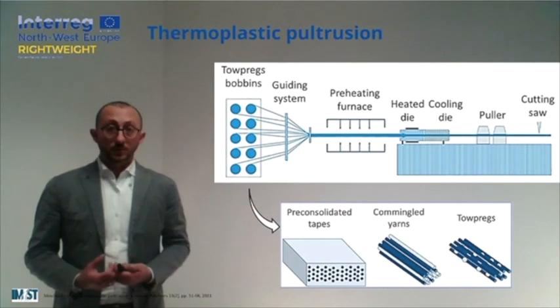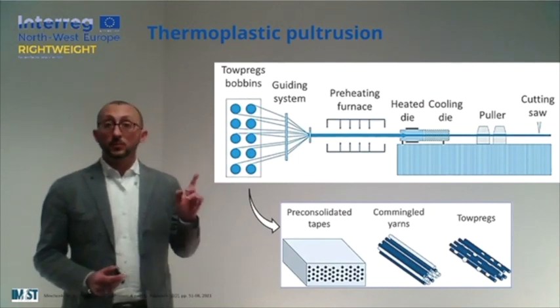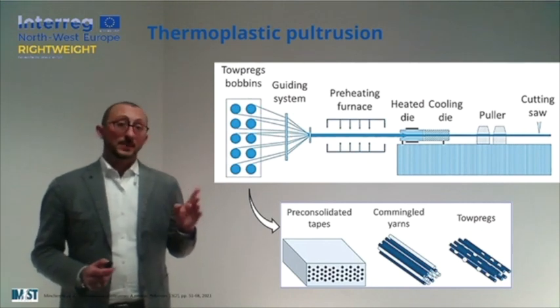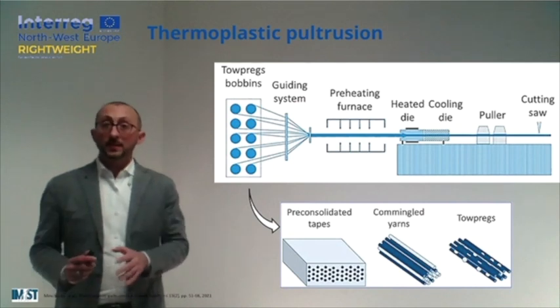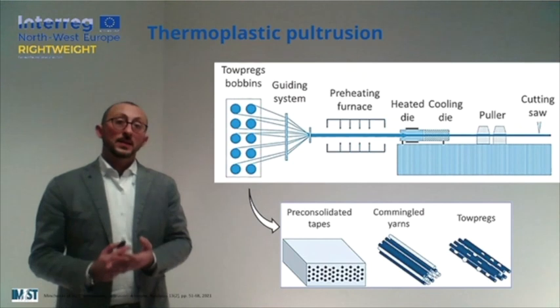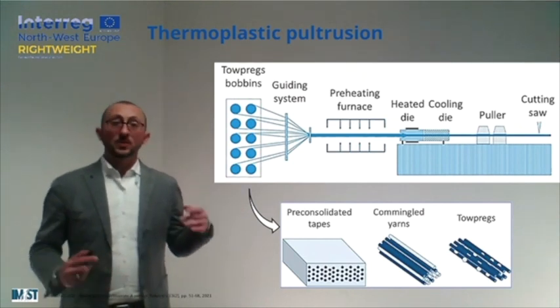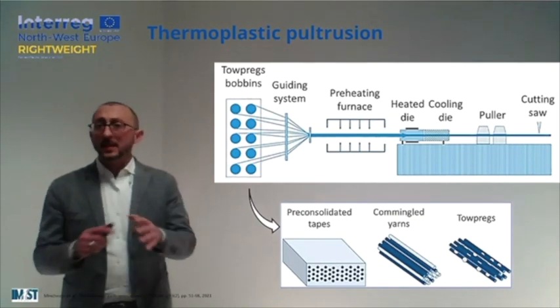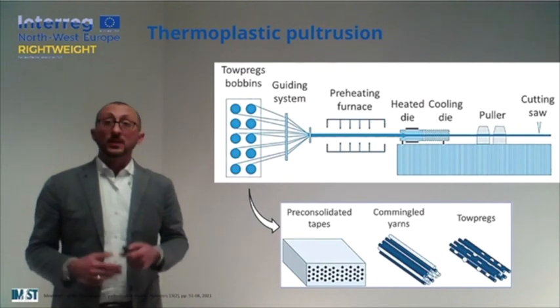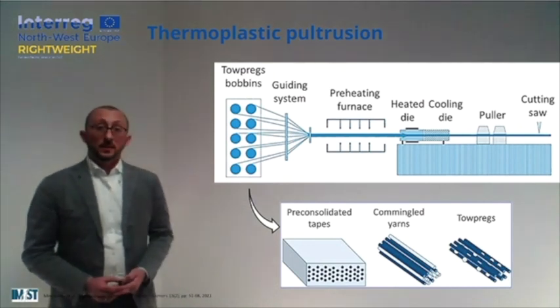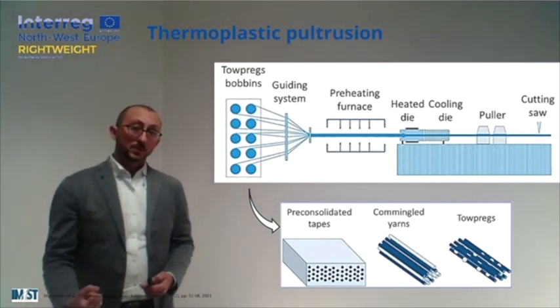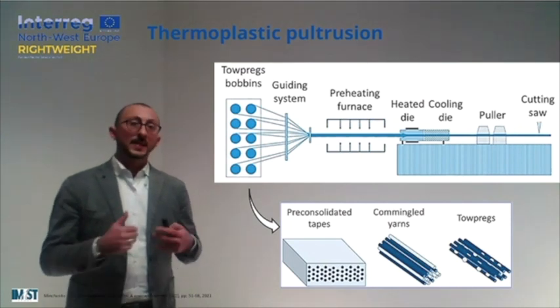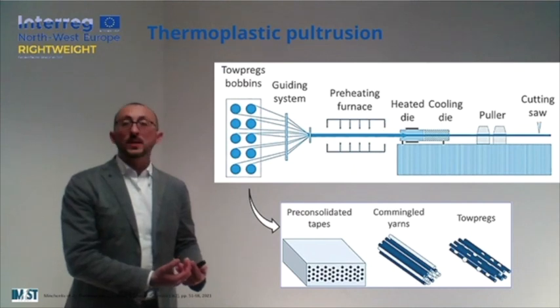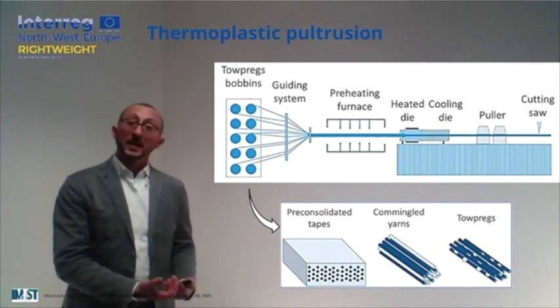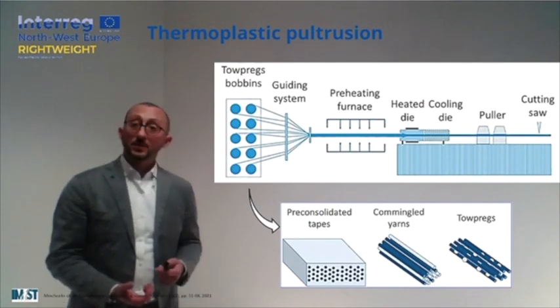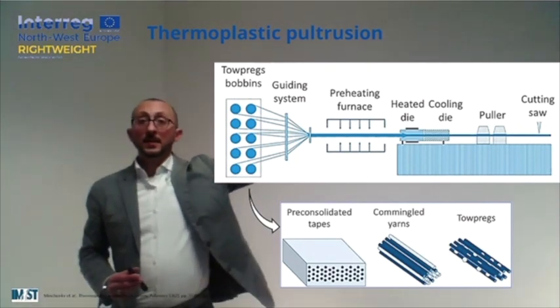So, in the most common approach, the starting point of our pultrusion line is given by the same creel rack, but on that creel rack a combination of matrix and reinforcement is placed in the form of tapes or commingled yarns or towpreg, but basically both of them should be there. And of course, keeping in mind that in order to shape a thermoplastic material, we have to reduce, first of all, its properties by heating it up, and then cooling the material down will give us the improvement of the mechanical properties. Another variation is necessary inside the heating and curing die over there.